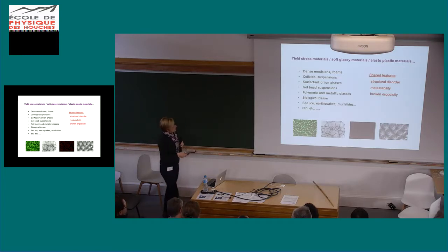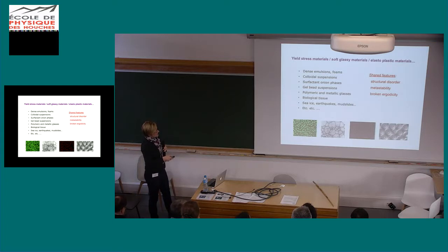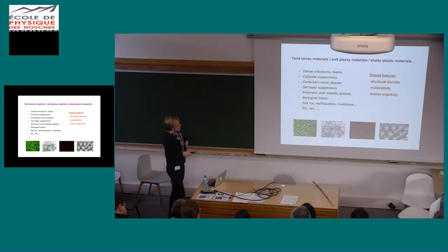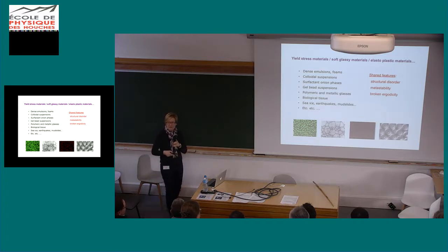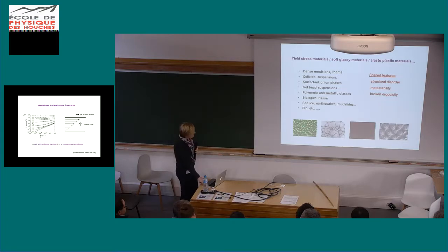And the basic notion here is that these materials share some features in common. If we focus for definiteness here on an emulsion with a high packing fraction of bubbles, we see that it's a structurally disordered packing. Because the bubbles are tightly packed together, they're stuck in metastable states and struggle to rearrange relative to each other. So they're in metastable configurations, and they can't properly explore phase space. So in the language of statistical mechanics, the ergodicity is broken.